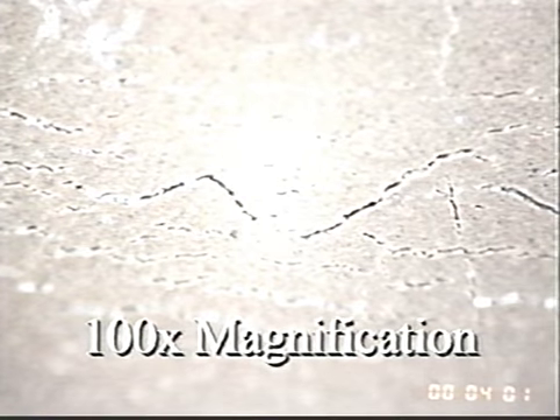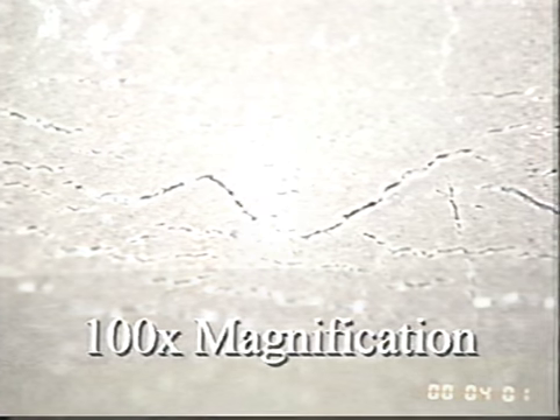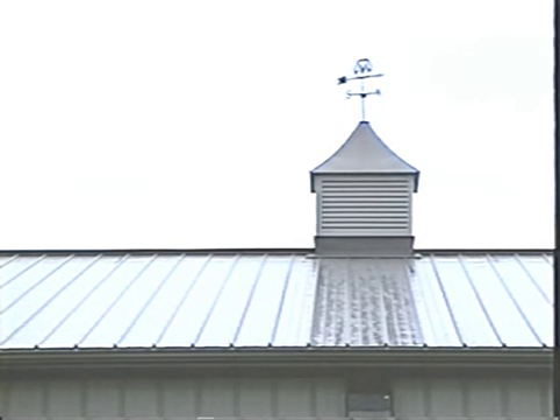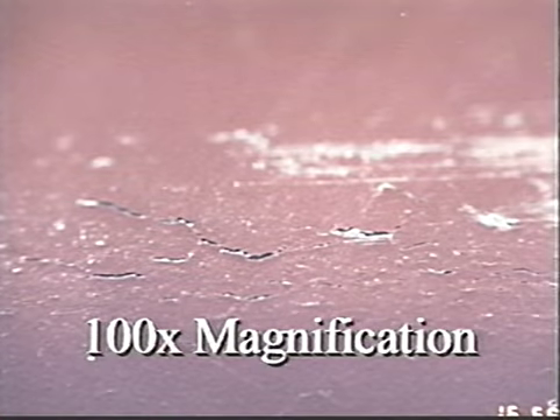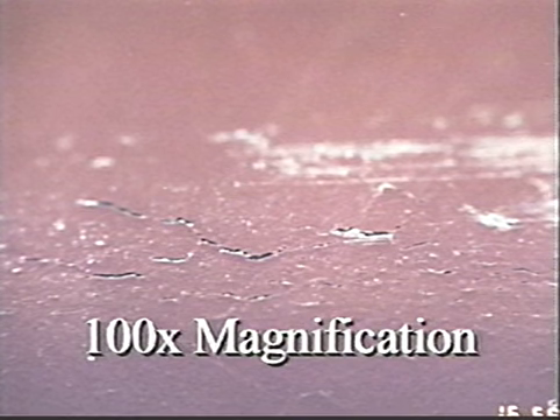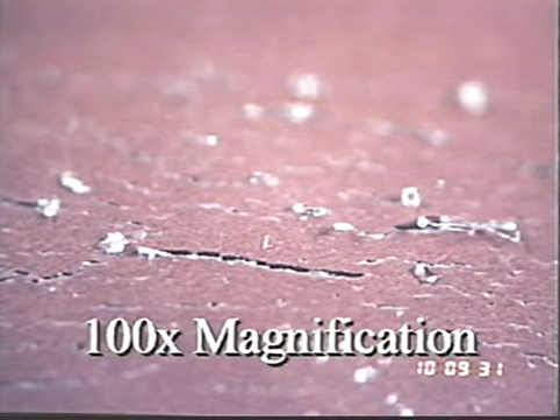But the stress of the additional bending and stretching to form their steel rib configurations causes even more dramatic hairline cracking in their paint, leaving their paint system more vulnerable to red rust corrosion. A serious problem can develop within these cracks. Long after a rainstorm ends, moisture remains on the roof. The flatter the pitch of the roof, the more water remains. The water then evaporates and contaminants are deposited into the hairline cracks. Eventually, the contaminants interact with the steel, and that's when red rust forms.